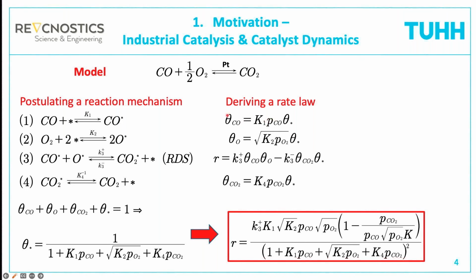And we do this using, for example, an adsorption isotherm, and then we can express the coverage of CO as a function of the partial pressure. And here we have oxygen, and here we have CO2. And now we can plug this all into the rate law, the rate determining step.